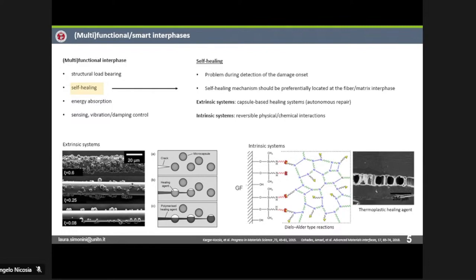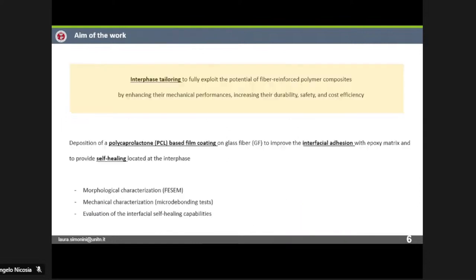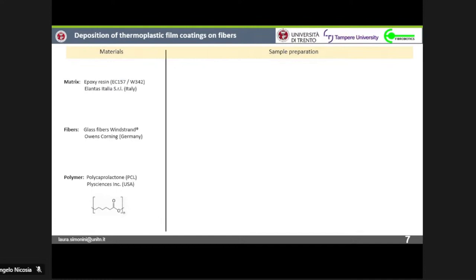The idea is this one: the application of a thermoplastic coating on the surface of the fiber. The aim of my work is to tailor the interface to fully exploit the potential of a fiber-reinforced polymer composite, and for doing this, we deposit a PCL coating on the surface of the fibers to improve interfacial adhesion and provide self-healing capabilities, so to delay the debonding and to prevent its propagation. We started from materials such as epoxy resin for the matrix, glass fibers for the fibers, and polycaprolactone as the interfacial healing agent.